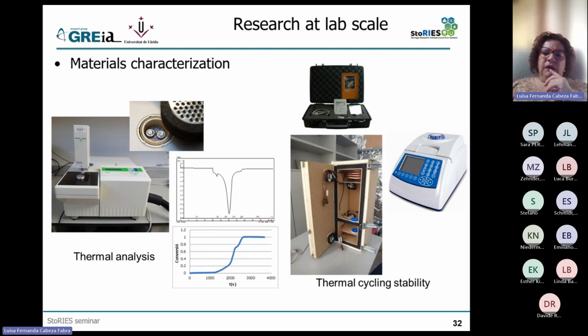And we developed this box that we call test box, where we can put our sample in the middle. We have heat flux sensors, and with these coils in the bottom and in the top of this we can produce the required temperature difference so that we produce a heat flux. This box is super well equipped with vacuum panels, 2 or 3 layers of them, to ensure that it's nearly adiabatic so that we have only unidirectional heat flux.